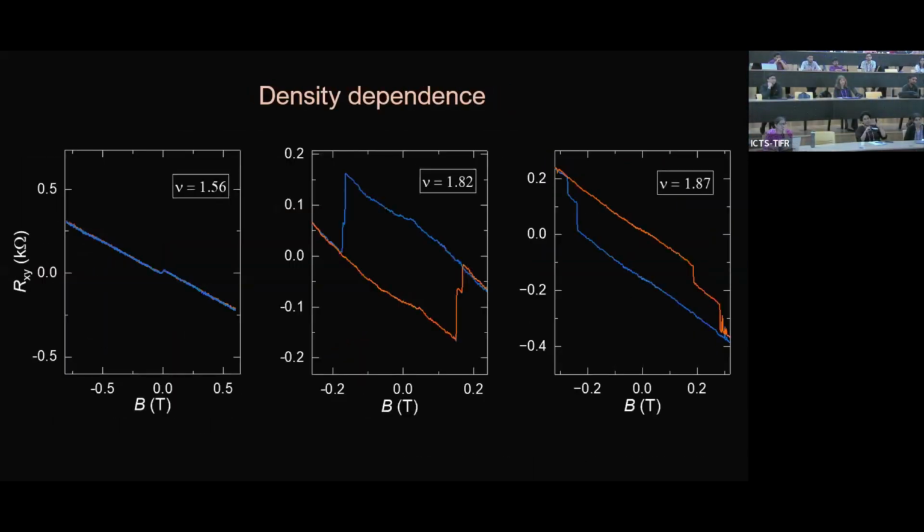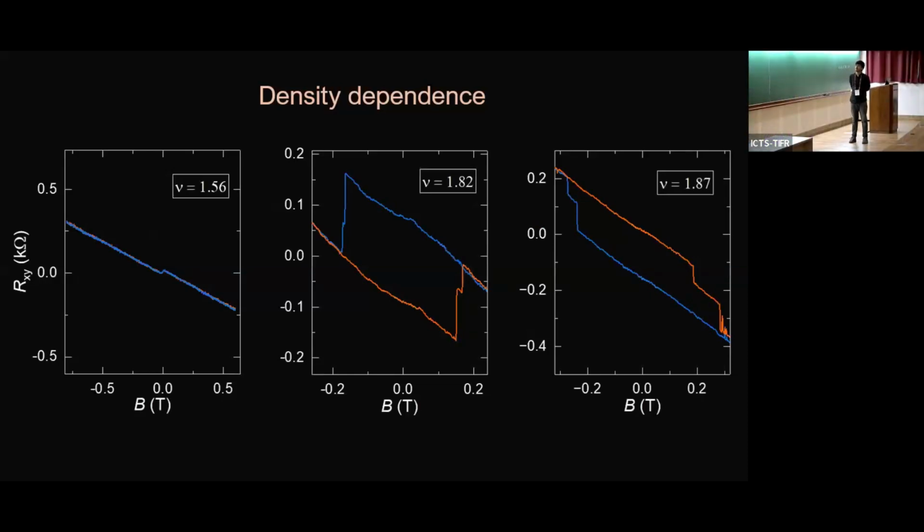So we thought that these are Barkhausen steps, but we don't know because these are coinciding with the RXY data I showed you, step-like structure in MR data. This could be because of the pinning of domain walls and twist angle inhomogeneity also, but it might be something related to the MR we are seeing, the complicated magnetic structure.